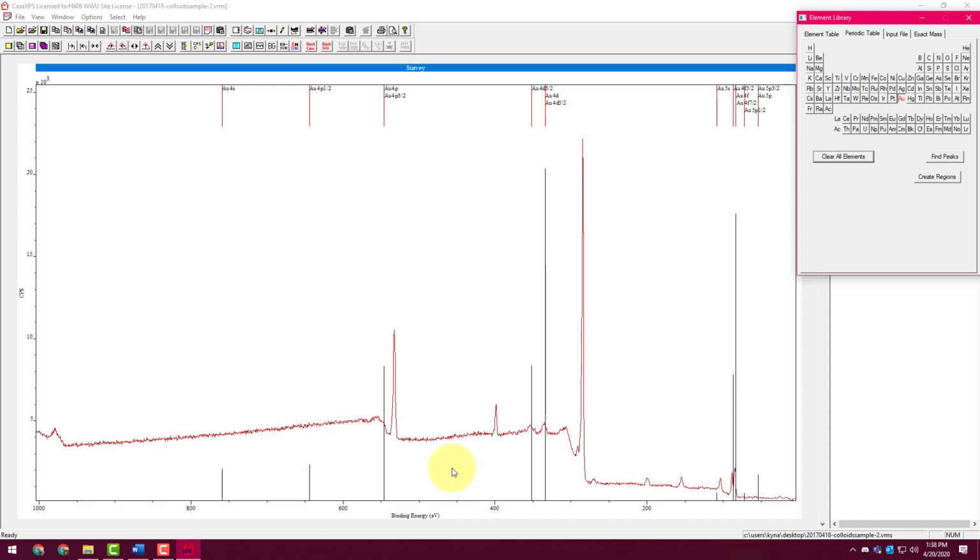And then these other peaks up higher, the 4P 1/2 and the 4S, are just likely too small for us to see. So I did say that you need all the peaks to show up, but if you have something, say gold, that's like 5 or 10% concentration in the sample, then it's going to be quite difficult to get the smaller peaks to show up above the noise. Now you should be able to eventually, if you just scanned for a really, really long time, lower the noise and increase the signal. But if you have several other peaks that line up, it's not really necessary.